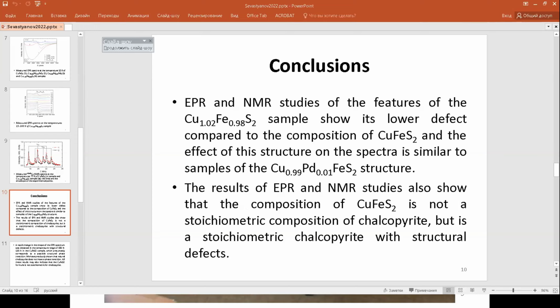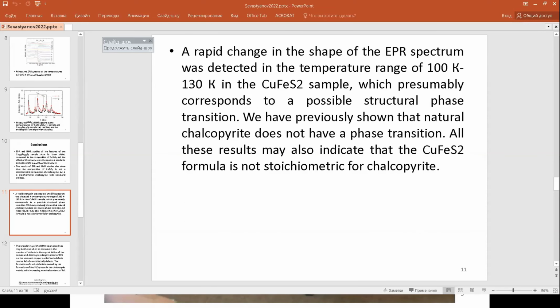The results of EPR and NMR studies also show that the composition CuFeS2 is not a stoichiometric chalcopyrite, but a chalcopyrite with structural defects. A rapid change of the shape of the EPR spectrum was detected in the temperature range of 100 Kelvin to 130 Kelvin in the sample, which presumably corresponds to a possible structural phase transition. We have previously shown that natural chalcopyrite does not have a phase transition. All this may also indicate that the CuFeS2 formula is not stoichiometric for chalcopyrite.